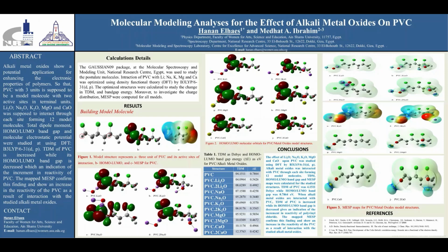Total dipole moment of polyvinyl chloride is increased while its HOMO-LUMO band gap energy is decreased, which is an indication of the increment in reactivity of polyvinyl chloride. The mapped molecular electrostatic potential confirms this finding and shows an increase in the reactivity of the polyvinyl chloride as a result of interaction with the studied alkali metal oxides.